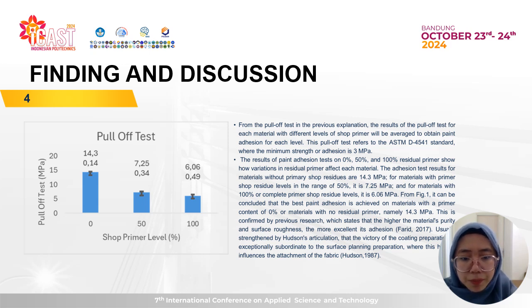It can be concluded that the best paint adhesion is achieved on material with a primer content of 0%, or material with no residual primer, at about 14.3 MPa. This is confirmed by previous research, which states that the higher the material purity and surface roughness, the better its adhesion. And it is usually strengthened by Hudson's argument that the success of the coating is exceptionally dependent on the surface preparation, which influences the attachment of the material.